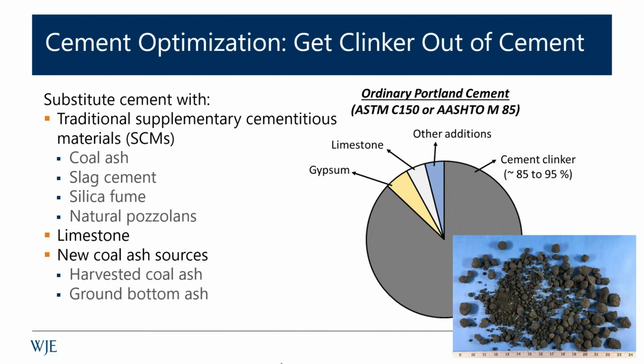Limestone's really not an SCM, but limestone can often be substituted up to a point with Portland cement, where you get an improvement in performance. And then as you add further limestone, you start to get a dilution effect, and you can start to see it degrade performance a little bit, to where maybe you get back to where you originally were. And then you have new coal ash sources, the harvested coal ash in ground bottom ash, as I mentioned. So these are all allowed under current specifications through either ASTM C595 for blended cements, or their respective spec for each of those materials.